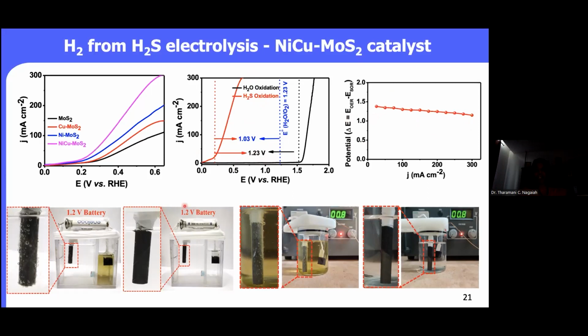So motivated by this, we removed the external power contact and we connected a 1.2 volt battery. And you can see here the bubbles on the electrode; these bubbles are due to the hydrogen production, and also the yellow color in the solution is due to the polysulfide on the anode side. Whereas in the absence of H2S, we did not see any bubbles. That means 1.2 volt is not enough for electrochemical water splitting here. And then again, we further shifted to the DC power supply, not only 1.2 volt; you can see that 0.8 volt itself is good enough to produce hydrogen in the presence of H2S, but we don't see anything on the electrode in the absence of H2S.